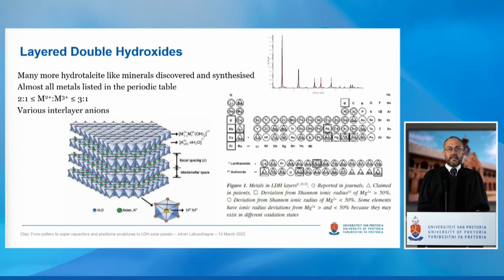As I said, hydrotalcite is made of layers, and these layers are typically brucite-like layers. Brucite is a magnesium hydroxide mineral, as we can dig it out of the ground. So in this brucite layer, the magnesium is isomorphically replaced by the aluminium in the lattice. This leads to a charge that is balanced by the anion. Now, layered double hydroxides in general still have brucite-like layers, but the divalent and trivalent metals making up these layers are different. They're not magnesium and aluminium.